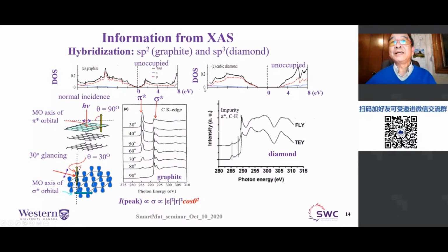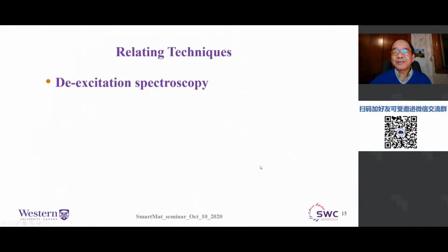Now, in the case of diamond, you don't have pi star, it's sp3 saturated. Then you can compare the density of states. It's very clear. Compared with the density of states calculation, you clearly see this feature that's very unique to diamond. So you know you have a diamond. And diamond normally does not have pi star, but if you have some impurities, you can see a little bit. So by doing the absorption spectrum, it can allow you to test the purity of the diamond, right? And this is what you can do. Okay, so those are the three most common applications of X-ray absorption spectroscopy.